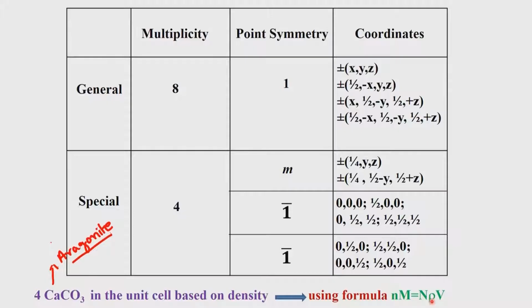There is always a possibility of going wrong in this assumption, because the software gives the density of the crystal based on the value of n. And suppose, let us say in this example n was assumed to be 8, then we will get a wrong density, because we know that n is equal to 4 by experimental determination of the density. So, how does one determine the density of a crystal?